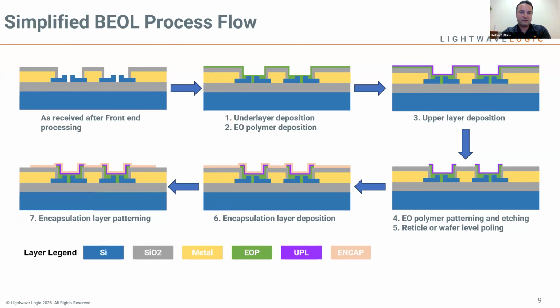So it's a pretty simple, and also simplified process that I'm showing here. There's obviously a few more steps, but all the tools, all the processes are standard to CMOS foundries. So it's really very straightforward to implement these deposition steps, the spin coating, and the encapsulation processes in the foundry. We use basically atomic layer deposition for the encapsulation, and for some of these other layers. So all tools that are now standard in the foundries.